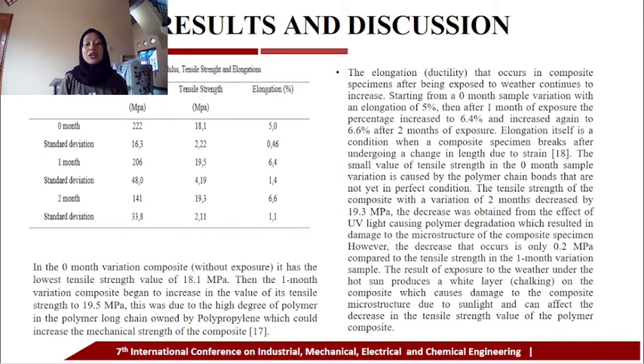The elongation or ductility that occurs in composite specimens after being exposed to weather continues to increase. Starting from a 0-month or without exposure sample with an elongation of 5%, then after a month of exposure, the percentage increased to 6.4%, and then increased again to 6.6% after 2 months of exposure. Elongation itself is a condition when a composite specimen breaks after undergoing a change in length due to strain.